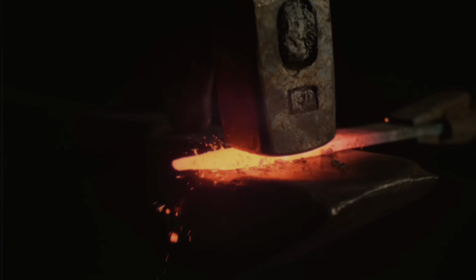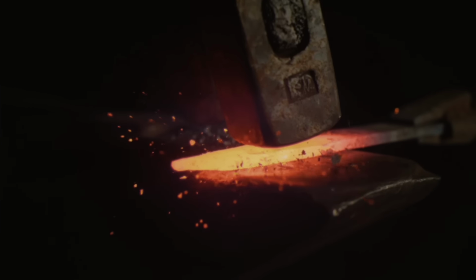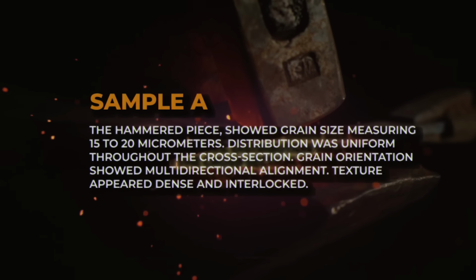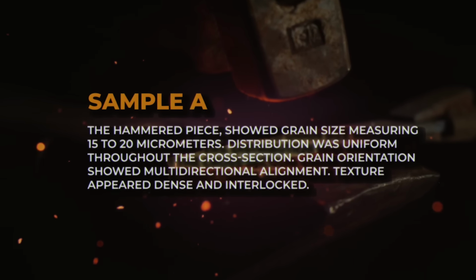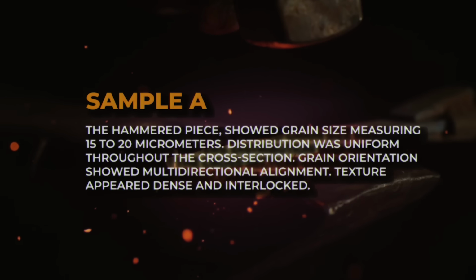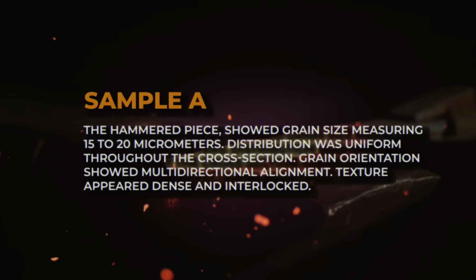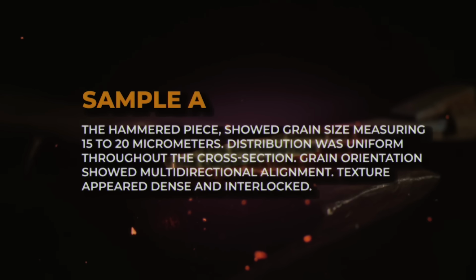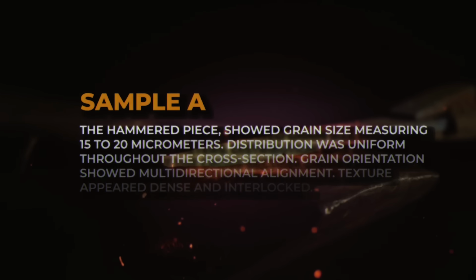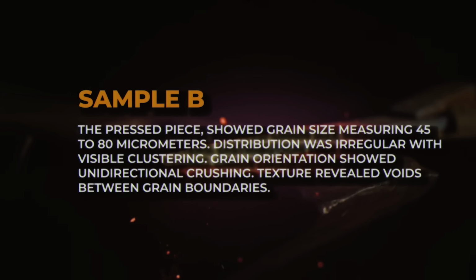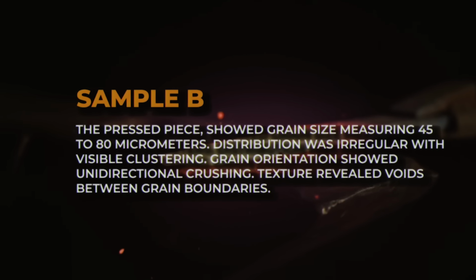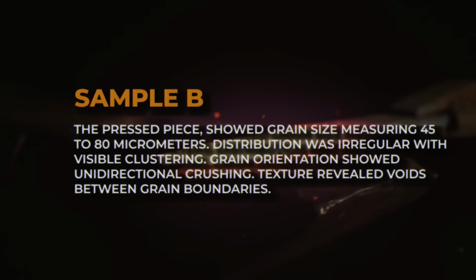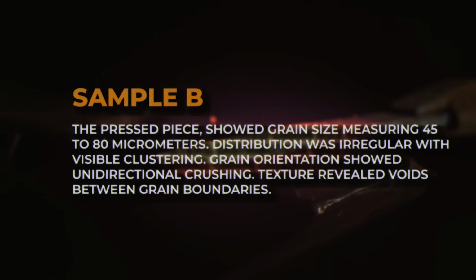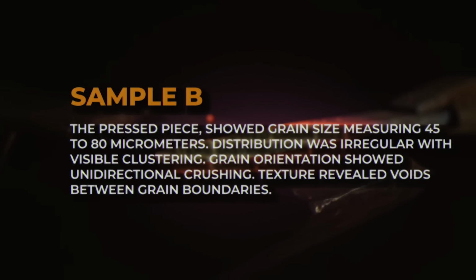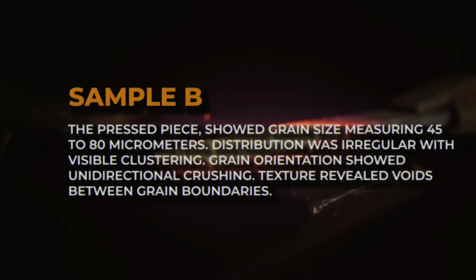Before destruction testing, scanning electron microscope analysis revealed the internal structural differences. Sample A, the hammered piece, showed grain size measuring 15 to 20 micrometers. Distribution was uniform throughout the cross-section. Grain orientation showed multi-directional alignment. Texture appeared dense and interlocked. Sample B, the pressed piece, showed grain size measuring 45 to 80 micrometers. Distribution was irregular with visible clustering. Grain orientation showed unidirectional crushing. Texture revealed voids between grain boundaries.